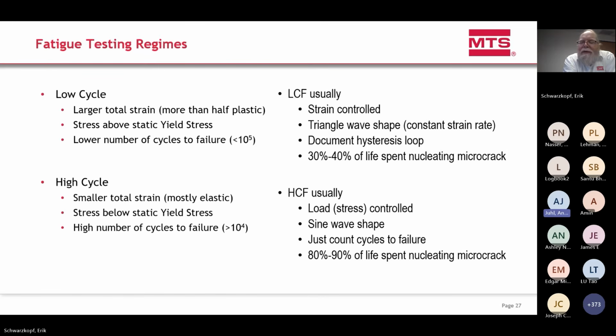And in low cycle fatigue, a smaller fraction of the life is used to nucleate a crack. The cracks initiate or nucleate fairly quickly in these specimens, and it takes a longer fraction of the life to grow that crack to failure, or a majority of life is spent growing that crack.